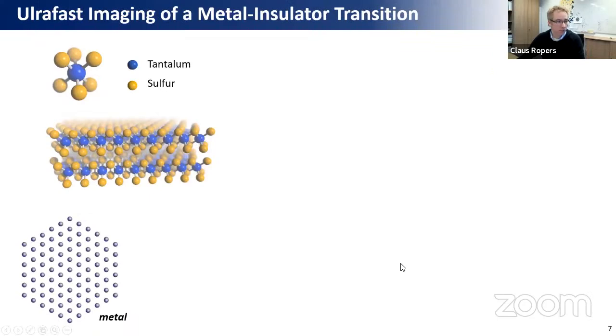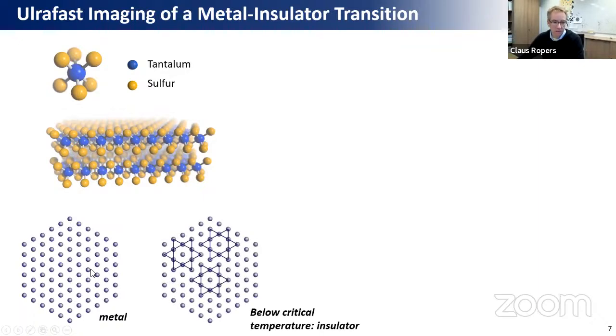Okay, so let me jump into this example a little bit more. It's about the ultrafast imaging of a structural phase transition coupled to a metal insulator transition in a material. So this is a 2D van der Waals material, tantalum disulfide, which is composed of tri-layer stacks of tantalum atoms sandwiched between sulfur planes and then stacked on top of each other. Basically, if you look on top of the tantalum atoms, they're given this kind of hexagonal regular lattice here.